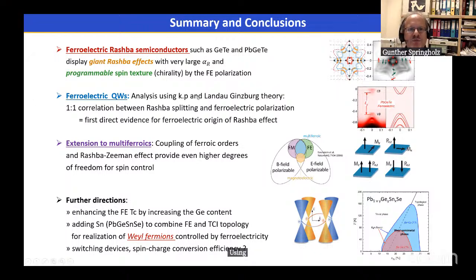Using k dot p and Landau theory, one can quite well explain these properties in the case of lead germanium telluride and lead germanium tin selenide. And we can also dope the system with magnetic impurities to induce ferromagnetic and ferroelectric properties at the same time. And this gives room to quite a large number of effects, Rashba-Zeeman effects, where the band structure is very much entangled by the different possibilities of the direction between the magnetization and electric polarization of the system.